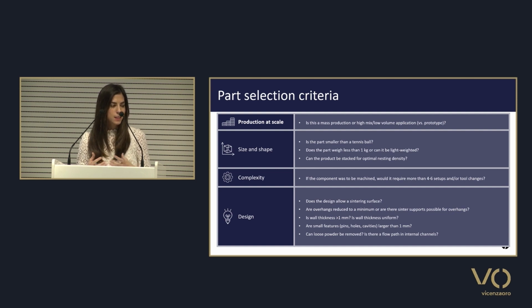Then looking at size and shape, the maximum recommended size that we give is a tennis ball size or a fist size of a part, because like this you can put many parts in a printer and take the full advantage of the productivity. We can print, of course, bigger parts than that, but maybe from a cost point of view, it will not be so efficient. Then from a weight point of view, as I was saying, we can produce parts of up to 1 kilo. Over 1 kilo, the sintering becomes a little bit challenging.